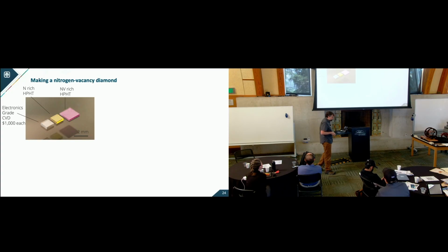The traditional diamond that everyone probably knows about is those made by high pressure and high temperature, or long periods of time, right? And so we can actually get nitrogen-rich, high pressure, high temperature diamonds. I have some of these to show you for the demo, but these come out with a yellow hue because of the defects in them. These have very few NVs in them. To make NVs, and we actually make a purple diamond, we take this yellow HPHT diamond, irradiate it with electrons, and anneal it, and then it turns purple because the emission spectrum is then more red, which is consistent with the NV.